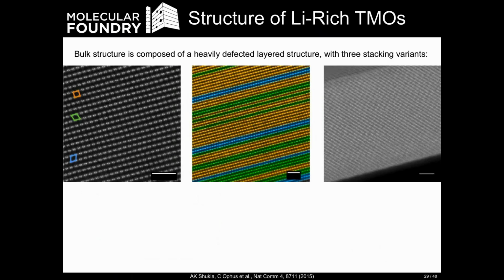In the upper left, I've shown the HAADF image. In the middle, I've colored it by the local stacking of these dumbbell structures. This just represents where the transition metals are in one of three sites, and lithium's on one of the three sites, and the TMs are on two of the sites, forming a dumbbell structure. I've colored it blue, green, and orange based on the different local orientation here.